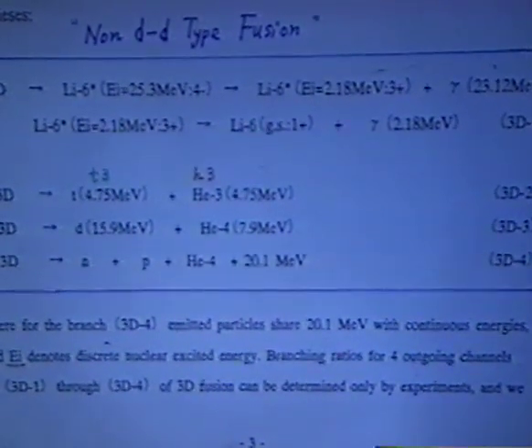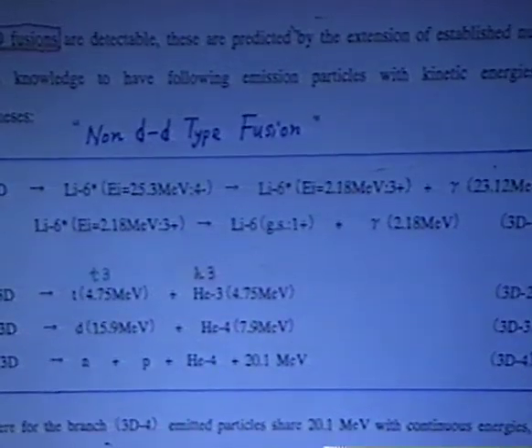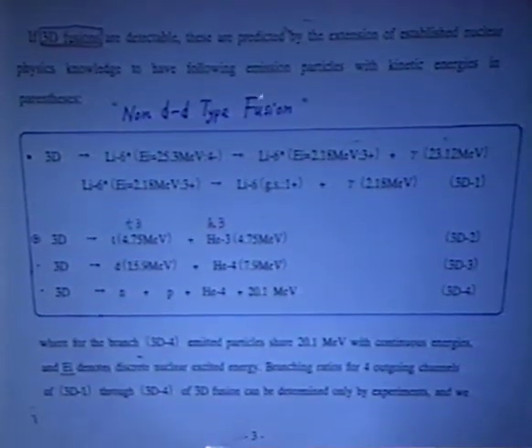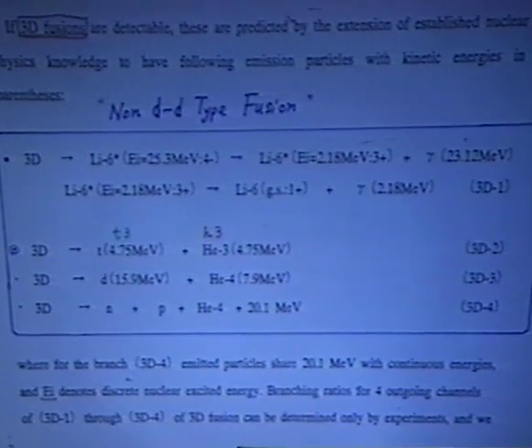Now, coming to the deuteron ion beam implantation type experiment to see the possible underlying nuclear physics process in so-called cold fusion experiments. This must be some kind of non-DD type fusion, because by using the known D plus D fusion, we can't explain the results. So I'll be assuming, for example, this kind of so-called multi-body fusion. This is a case of 3-body fusion with outgoing branches, one going to the lithium-6 ground state via electromagnetic transition, and the other 3 emitting high-energy charged particles. In this case, with our latest experiment,